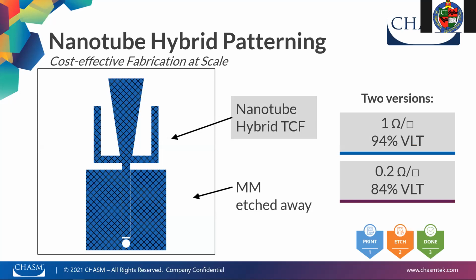We have two versions of the nanotube hybrid materials that are available for antennas, specifically designed for antenna applications. One of them is 1 ohm per square and offers 94% transparency, or VLT. And we have another version that's 0.2 ohms per square. This has a slightly lower VLT at 84%, but the pitch on this is much finer, so it can support very fine level details.